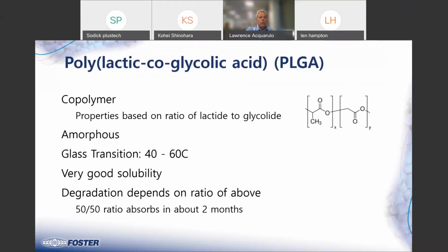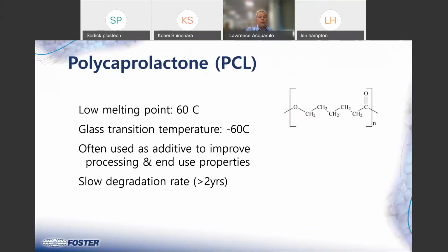You can copolymerize the two, PLA and PGA, and get every range in the middle. And typically a 50-50 ratio gives you something that absorbs in about 2 months. Polycaprolactone has a low melting point, and that's very important if you're trying to put a drug in the polymer. And you might use polycaprolactone as an additive for one of the other polymers, again, to change the properties and also to change the absorption rate.